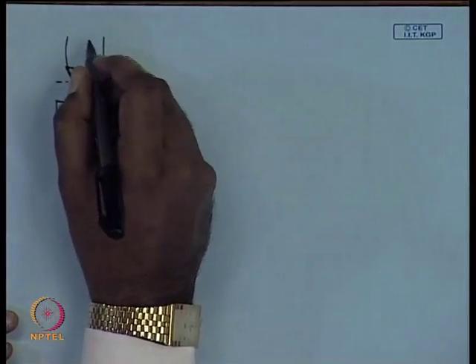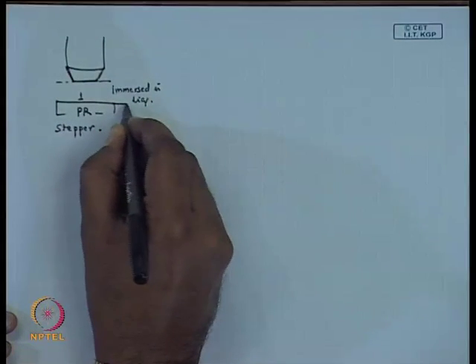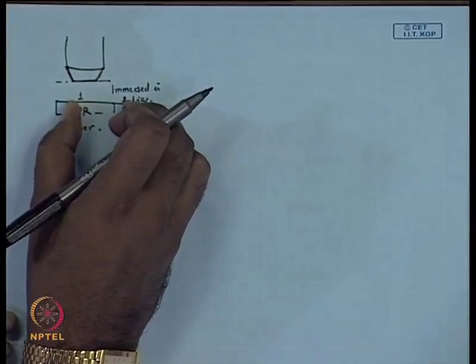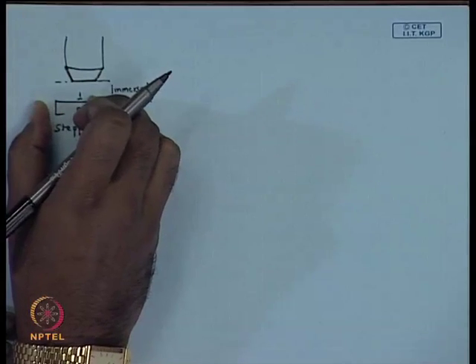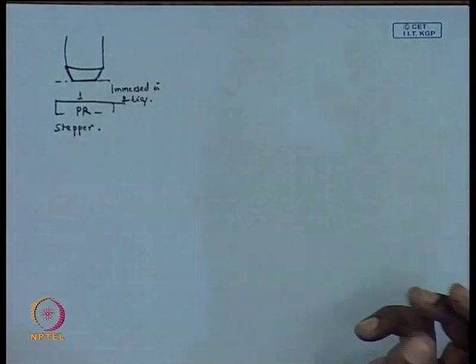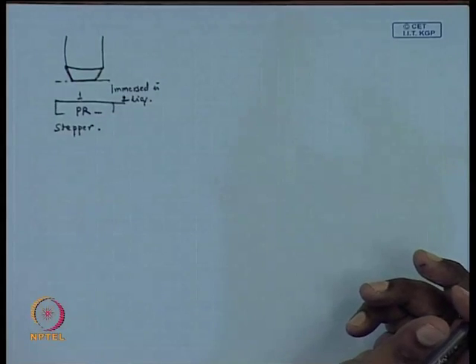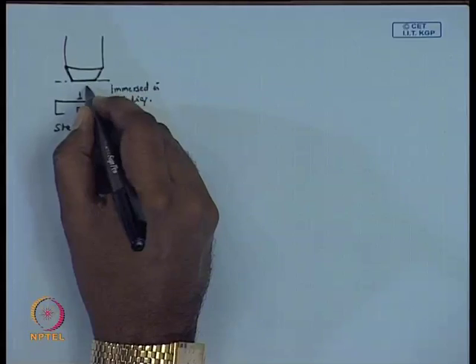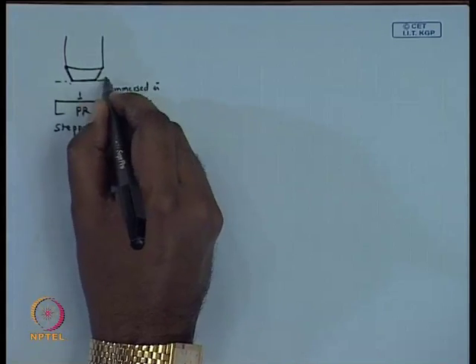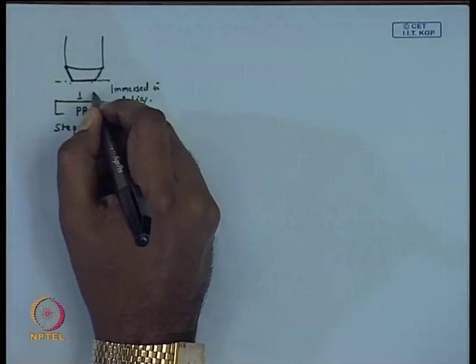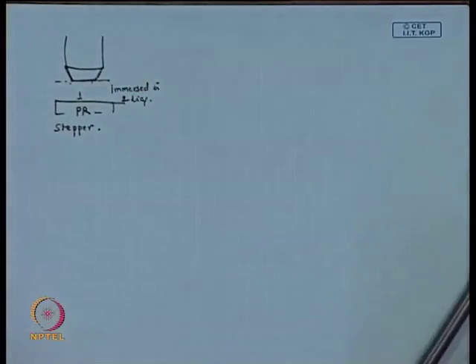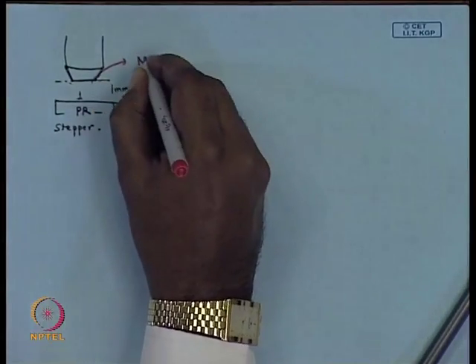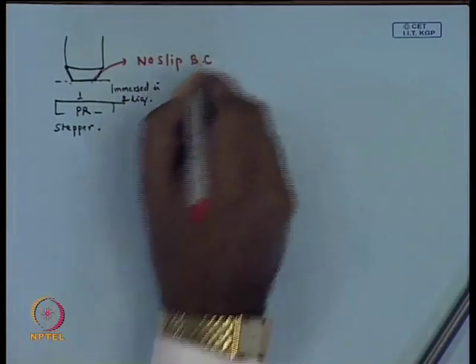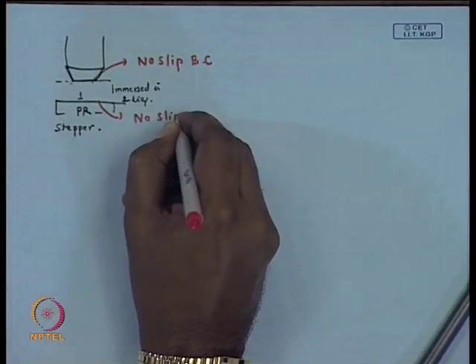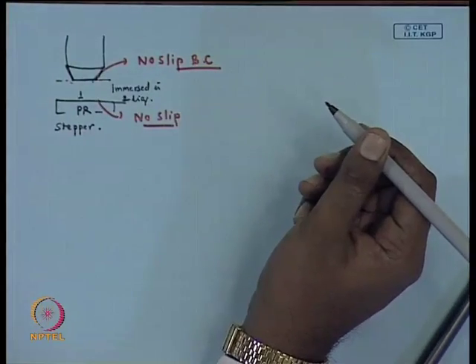So, once your exposure is done at one location, what would it like to do? Let us say this is location 1, somewhere down here is location 2. The stepper would like to move from position 1 to position 2, right. Now, the critical question to ask is, in an industrial process you would also like to optimize the time, but how fast or slow should the stepper move? Because if the stepper moves too fast, there might be a meniscus failure, or the meniscus between the lens and the resist layer might get detached. If you look back to your basic fluid mechanics concept, the no slip boundary condition is valid at both the interfaces because of viscous effects and things like that.